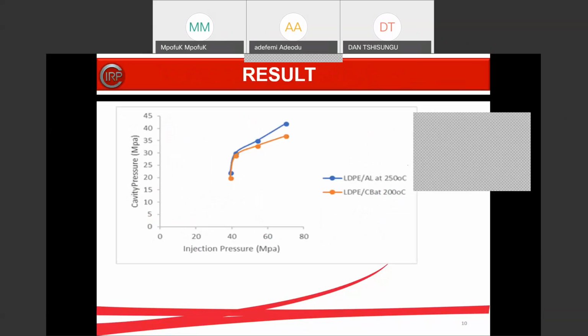Now, from the result, we can see that for the effect of injection pressure on the cavity pressure, the higher the injection pressure, the higher the cavity pressure for both materials. But we discover that the responsiveness of aluminium mixed with low density polyethylene is higher compared to carbon black mixed with low density polyethylene. This is because the injection temperature of aluminum is higher, and this actually tells on the viscosity of the low density polyethylene aluminum material.